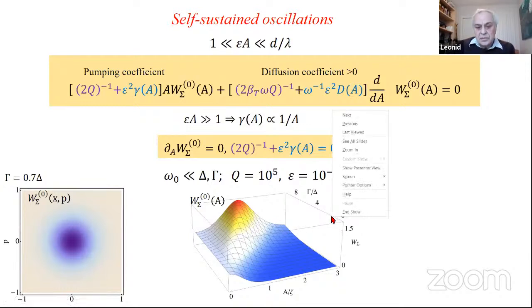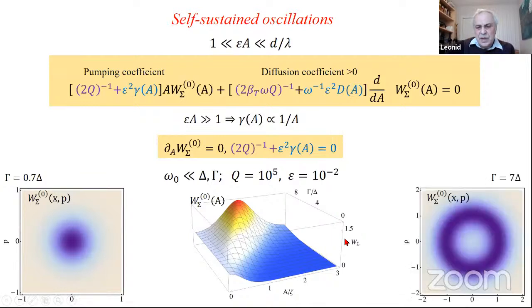This corresponds to this picture, and this corresponds to the excitation. Of course, again, everything depends on the direction of the bias voltage. All this picture we obtain for a positive direction of bias voltage, but if we change the direction of bias voltage, we can jump from this regime to this regime, or from this regime to this regime. So keeping the system at the same parameters and changing the bias voltage, we can get either the self-sustained excitation regime or the cooling regime.